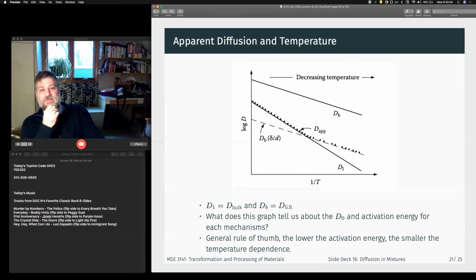Right, we see the same thing here for diffusion. The effective diffusivity, the slope for bulk diffusion is going to be much steeper here, which essentially tells us that as we get to higher and higher temperatures, our bulk diffusion is going to be dominant. And our overall diffusivity is not going to catch up to the grain boundary diffusivity except at very low temperatures. So if we extrapolate this out, eventually these two curves will meet.